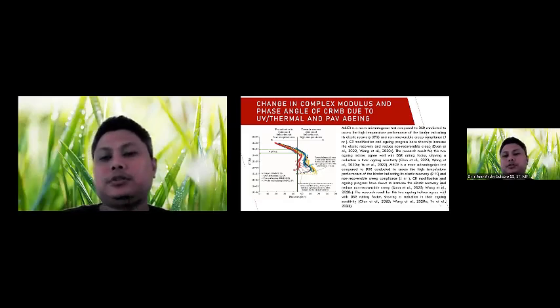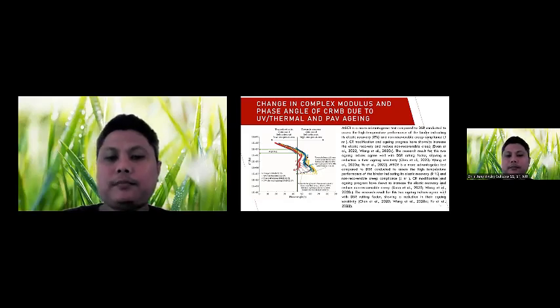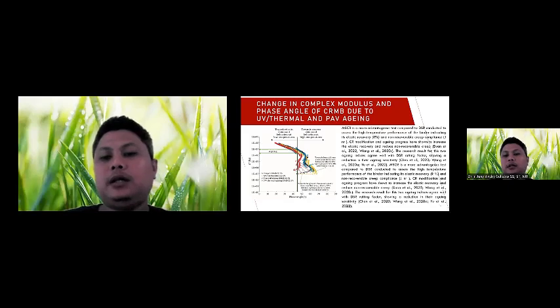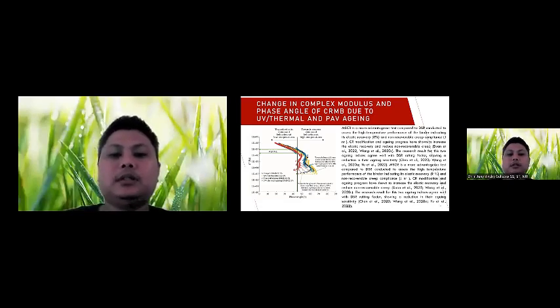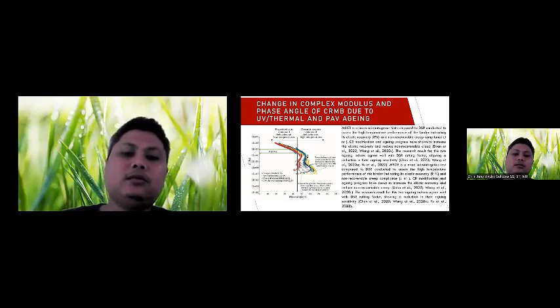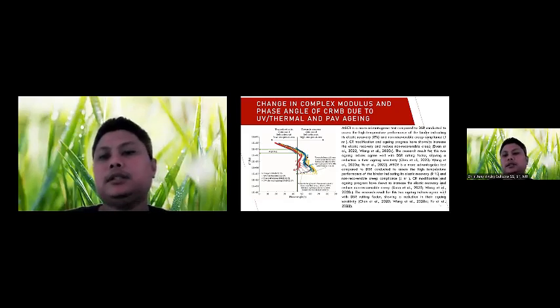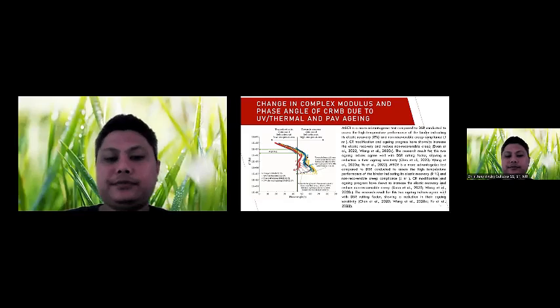For the next test, there is MSCR, because the MSCR is conducted to assess the high temperature performance of the binder, indicating its elastic recovery. CR modification and the aging process have shown to increase the elastic recovery and reduce non-recoverable creep. The aging results agree well with the DSR rutting factor, showing a reduction in aging sensitivity.